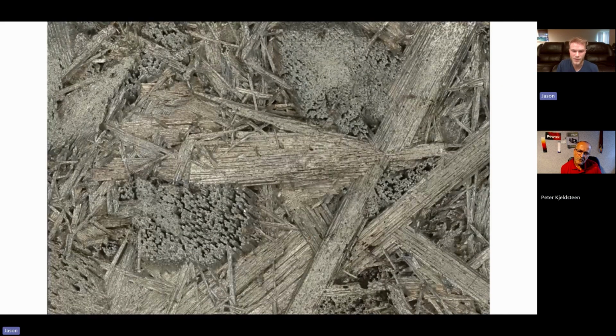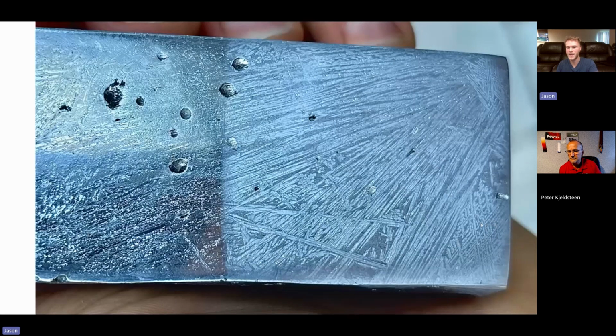Those individual crystals are the same shape of what we see there. So these rods are actually made up of all individual crystals that have a very similar shape. And you see it's like a diamond shape on each of the crystals, almost like needles. And then of course here there are voids, but deep inside the material, this would be filled with eutectic, right? And so that leads me to believe that this may be just a face of one of these